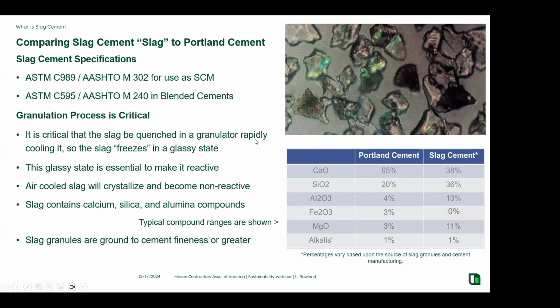The granulator that I mentioned is very important. You can't take the slag from the blast furnace and let it just air cool, because it becomes inert. It's essentially a rock at that point. It's not nearly as valuable because it's essentially inert. It could be used for fill and those kinds of things. But if you install a granulator and you freeze the chemistry through the quenching process, it becomes very much like Portland cement. The reactive materials within it have essentially the same mineral ingredients, but at a different ratio. So it doesn't have as much calcium, but it has the silicates. And of course, when you grind this very, very fine, it is a cementitious material.